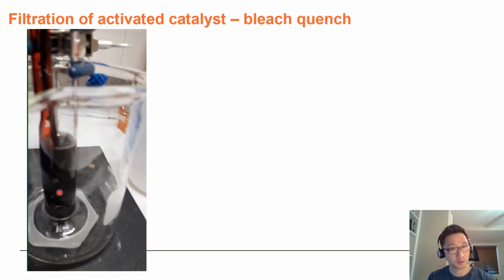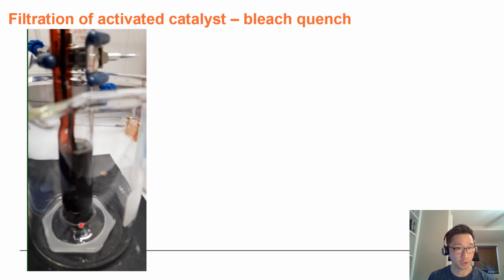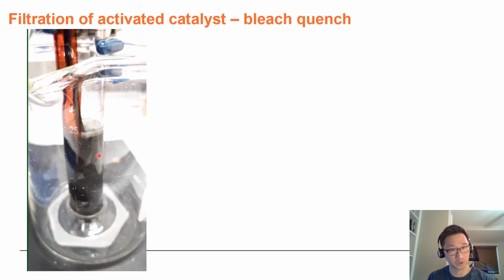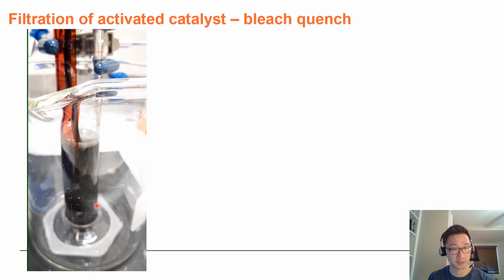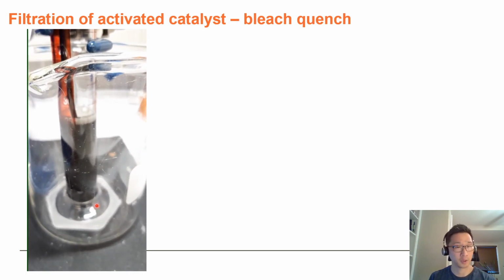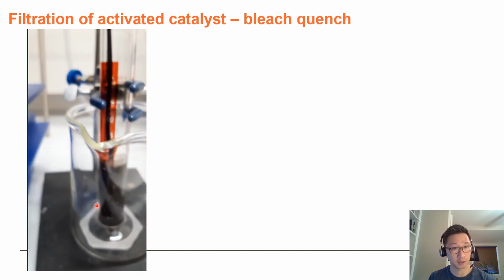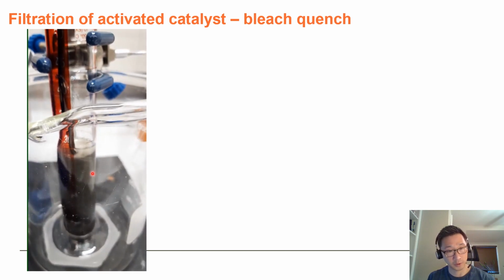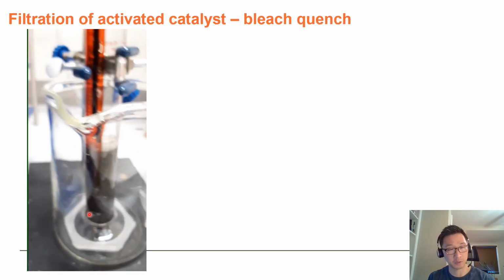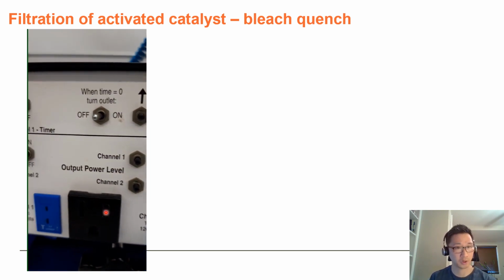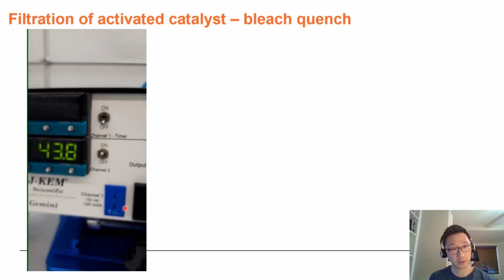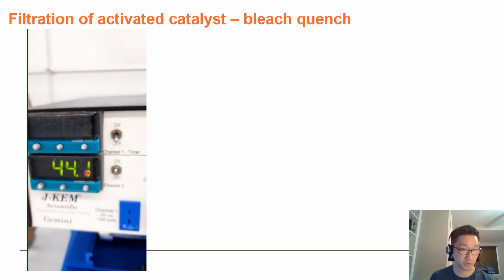Now, this is concerning. You don't want this to be happening in your reactor. It's not too dangerous here in the fume hood, but you don't want all this off-gassing to happen when you're trying to quench the catalyst in a reactor. What's also very concerning is that the temperature of the slurry was about 20 degrees at the start before the addition of the bleach. Upon adding the bleach, you notice very rapid exotherm in excess of 20 degrees.